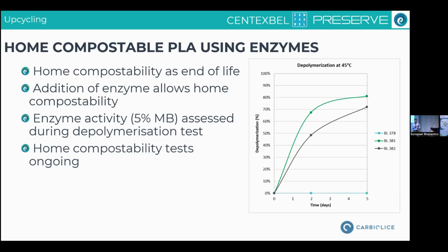However, with the second batch, this was completely solved, so we were able to extrude a PLA containing this enzymatic master batch. And what you see here on the slide is a first screening that Carbiolice performed regarding depolymerization. You see the reference PLA on the bottom in blue almost does not depolymerize under these conditions, while addition of about 5% of this master batch drastically increases the speed of depolymerization. These samples are now also submitted for home compostability tests, but the evaluation of these materials under home compostability is still ongoing.